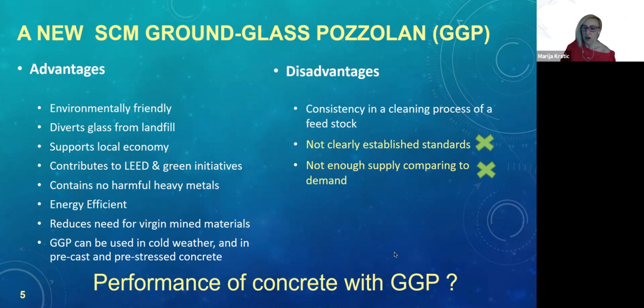Some of the challenges that we have faced along the way were consistency in the cleaning process of the feedstock, which is very important. We did not have clearly established standards when we started this study. However, we managed to approve an ASTM standard for ground glass pozzolan in concrete, C1866, and this standard was approved in December 2019 and published in April 2020. We also didn't have enough supply compared to demand in order to be able to use it in field applications. However, in December 2020, the first large-scale plant that produces this material opened.